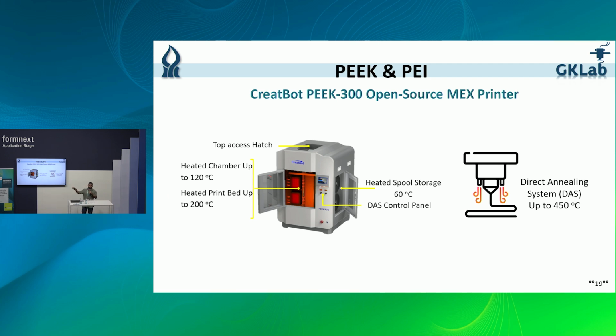And to print these polymers, we use a high temperature printer. This printer can reach a printing temperature of 450 degrees Celsius. This printer is also equipped with a convection heating system that works like a heat gun. It reduces the thermal gradient around the printed parts. And this is an open source printer, and most open source printers don't come with preset parameters from the manufacturer, and for that we need to perform a parameter optimization for each material that we use.